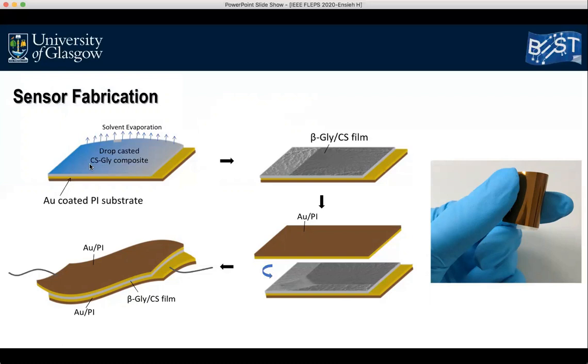of glycine chitosan was drop casted onto the flexible substrate, and then the solution was dried at room temperature by evaporation, and glycine crystals formed an ordered crystalline structure inside the chitosan. So after crystallization, another gold PI electrode was put on top of the film as a top electrode, and here shows the final structure of the sensor, which had very good flexibility.